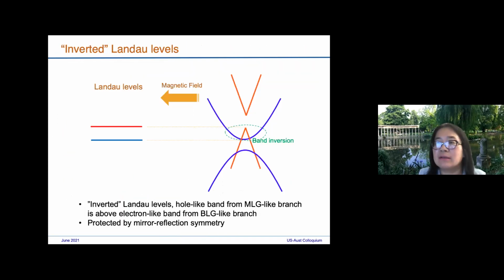bilayer graphene. In that case, you stress that gap opening for the red curve is band inversion, but it also appears for the blue curve too. The gap opening for the massive. Oh, you mean here? Yes, it's also the band inversion. That's a good point. But I guess because we're staying at zero charge density, so n equals 0 is somewhere here. So that's mostly what we have been studying. It's basically the phase diagram at charge neutrality point.